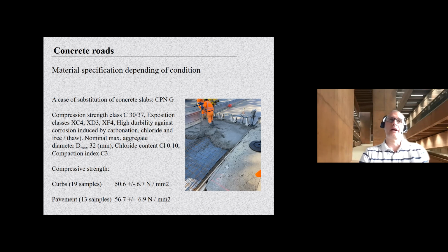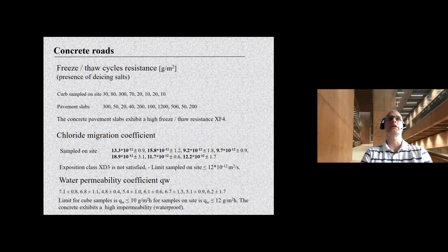We had a maximal aggregate diameter of 32 millimeters, and the workability index was good. We measured compressive strengths on the curbs and the pavement, and you can see the mechanical properties are well above 50 megapascal, which is actually a very high resistance for this type of concrete.